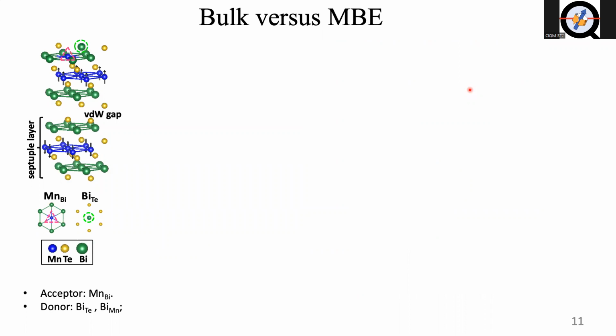So let me recap again about the manganese bismuth telluride structure. Here is the lattice structure. You can see that the manganese atoms form a well-ordered lattice, and we call each unit cell the septuple layer. It consists of tellurium, bismuth, tellurium, manganese, tellurium, bismuth, tellurium, and you can think of it as manganese telluride intercalated into bismuth telluride to form manganese bismuth telluride.